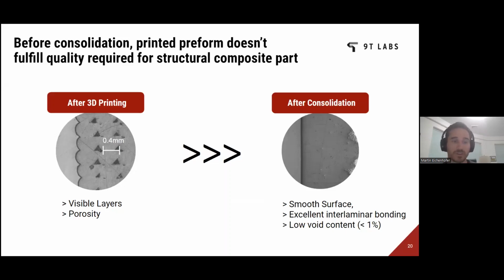So surface finish, you see here after printing, you still have the classic pattern on the side. The surface finish has this kind of bead, like the washboard. I mean, in German we say washboard kind of pattern. And you see also that internally we have some voids, and there is porosity, and the interlaminar bonding is also not as good as what we know from an injection molding part, for instance.